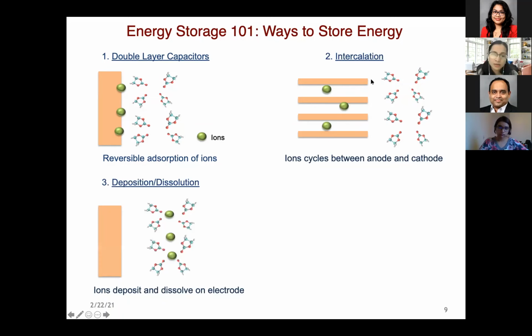Another thing we can do is something called deposition dissolution. You can think of it as lithium or copper ions coming in and plating on the surface. Now we are storing energy using high energy chemical reactions, so the amount of energy stored is very high. But unfortunately, every time we charge and discharge a battery, we are in a way messing up the morphology of the electrode, due to which the cycle life is very limited.